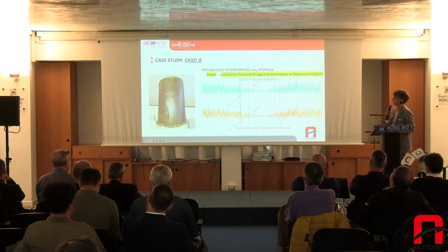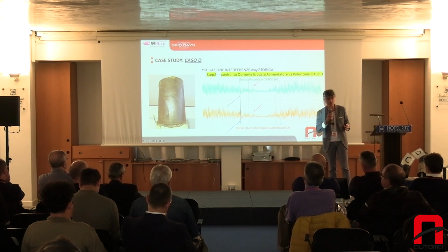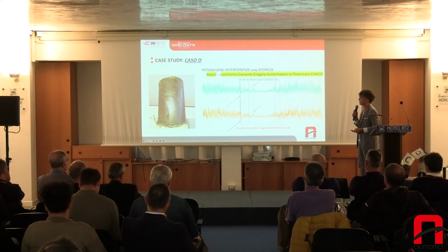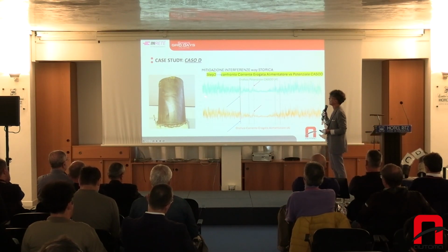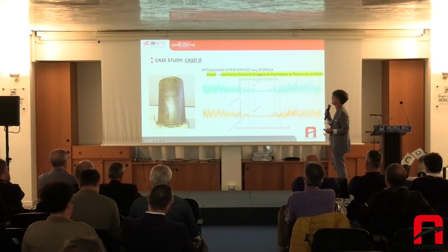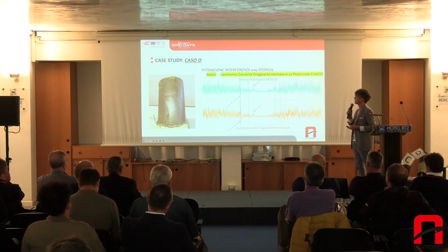In all these circumstances, like here, for example, where I have 6 amperes, so when there is a reduction in current on constant potential, I have entering current on the pipe. So I have a cathodic current in this condition. And here I have minus 1.5, so the potential value is cathodic. In this case, I have a positive value on the top.